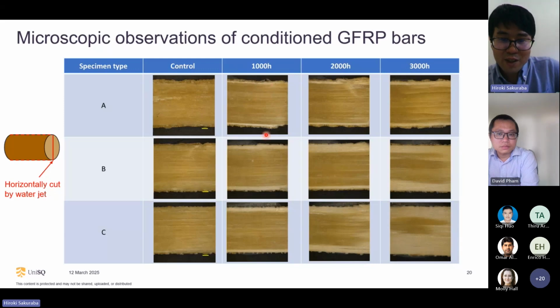This white color area means damaged area. I observed this white color area had resin damage, fiber filament damage, and interface damage. As the conditioning time increases, the white damaged area increases. And as you can see, specimen type C has the highest damaged area. So by using the digital microscope, we can observe the damaged area, and this can help understand the degradation mechanism.